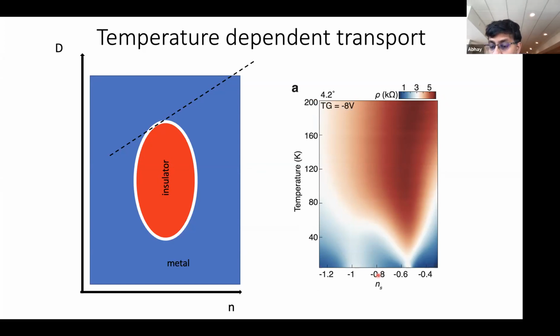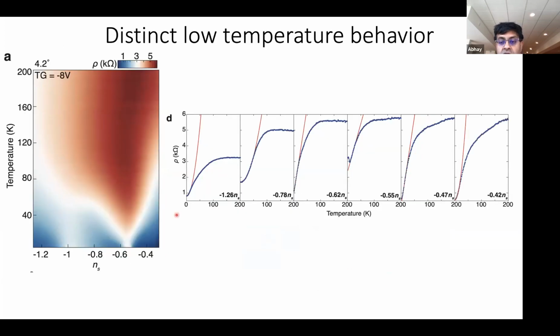Now, you can go down to low temperature and you can look at the behavior of the resistance as a function of temperature and try to distinguish different regimes of behavior, whether it goes as T or T squared or whatever is the power of temperature. And so I'll show you here a few cuts taken at different values of doping. And let me point out what these cuts correspond to. If I sit beyond the band insulator, so this is some random place which is at very high doping, and you go down to low temperature, you'll find that the resistance as a function of temperature goes as T squared at low temperature. Now, this is coming closer to the half-filled insulator. So this is somewhere here between the band insulator and the half-filled insulator. If you measure resistance as a function of temperature, once again, you see nice T² behavior at lowest temperature.